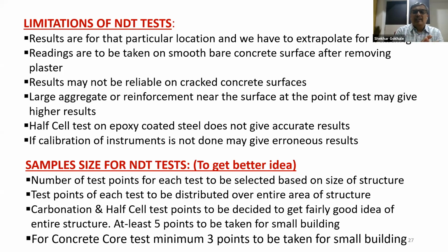So you should not take the reading directly on the cracked surface. It should be adjacent to the cracked surface. Then if large aggregate or reinforcement is near the surface of the point of test, then we are likely to get higher results. So sometimes what we do, we take 2-3 different readings in the nearby area and then average it out to get a value for that particular test location.